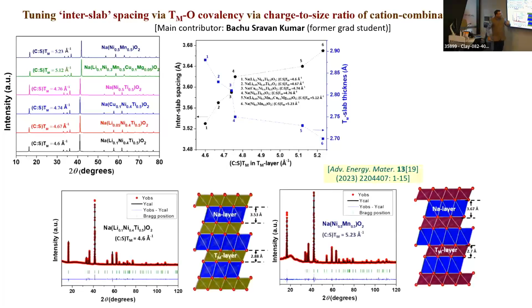Okay. So now, if I look at the structure, I can see that it agrees with my hypothesis, in the sense that when I have a low charge to size ratio, my inter-slab spacing... So this is my inter-slab spacing in the battery. Like the battery community, when one looks at this layered transition metal oxide, one refers to the transition metal oxygen layer as slab, and the alkali metal ion layer as interslab, as if between the two slabs. So when I say interslab spacing, I mean the sodium layer.